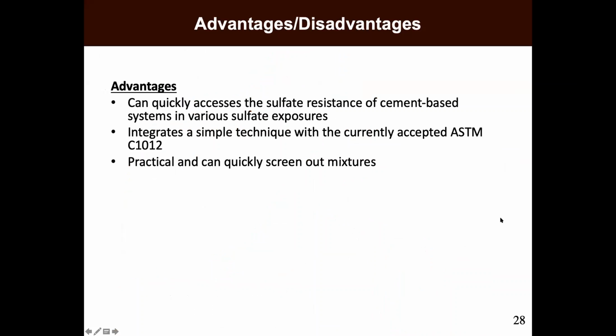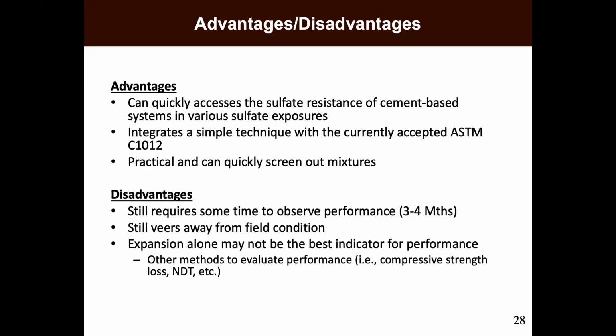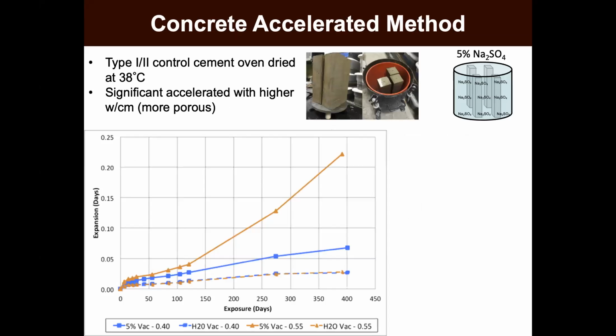And so again, the advantage and disadvantage: you can quickly assess sulfate resistance faster. It's a simple technique that doesn't require much change from the 1012 method. It's very practical and can quickly screen out mixtures. Some of the disadvantages in this case: it still takes some time. Obviously, it still veers away from field conditions because we're still using mortar bars. However, we have looked at ways of doing it with concrete.